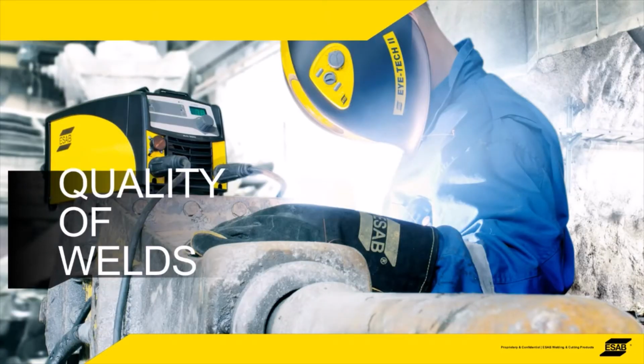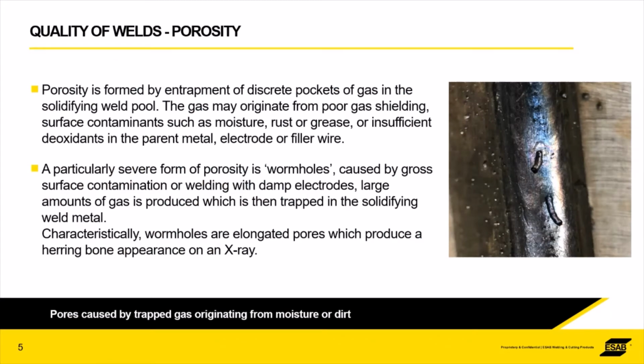So quality, what's this all about? The main worry with any kind of filler metal is dirt and water. If you get dirt and water in the weld, then that's a source of gas. As soon as the arc hits it, you're going to be creating gas. Gas creates pockets within the molten metal, so you end up with porosity. A particularly nasty type of porosity we can see there is a wormhole. So this is a big amount of gas or a big amount of dirt.